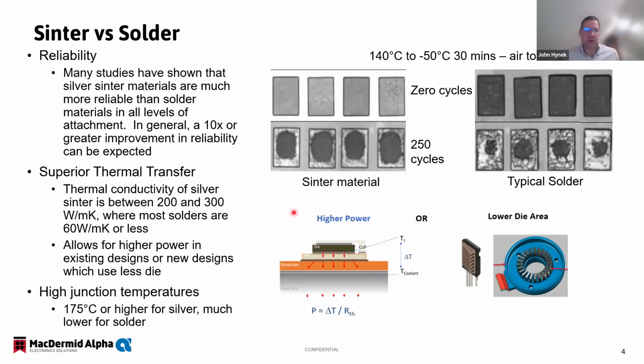The third advantage you get is the ability for higher junction temperatures. Silver sinter will withstand 175 C just fine for pretty much any amount of time. There really isn't a solder on the market that you would want to run at that high of a temperature for that long. So those are your three main differentiators between sinter and solder.